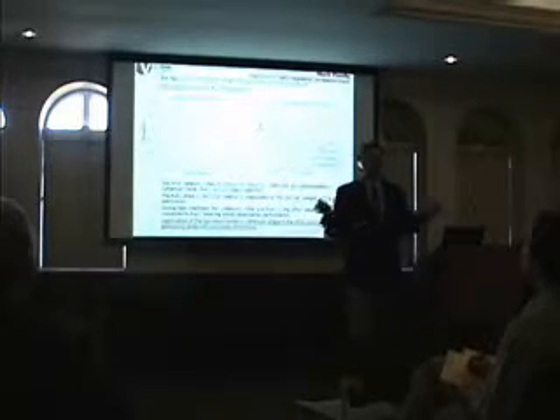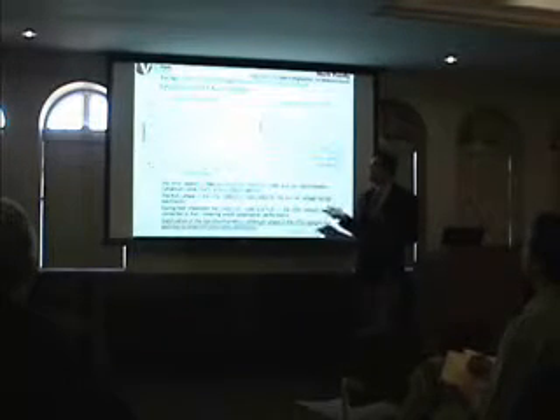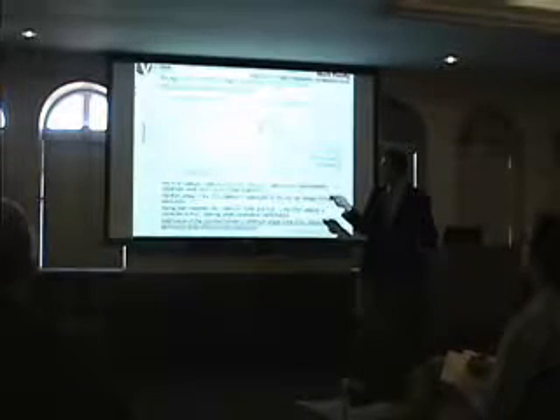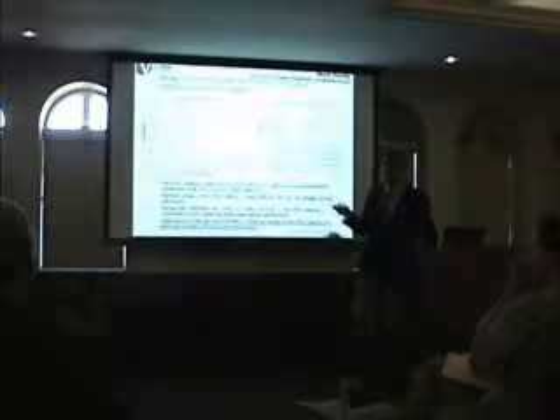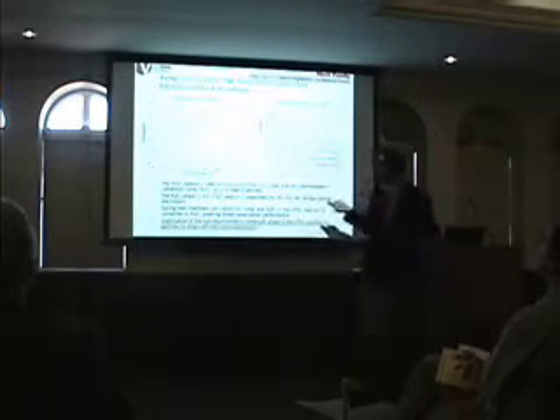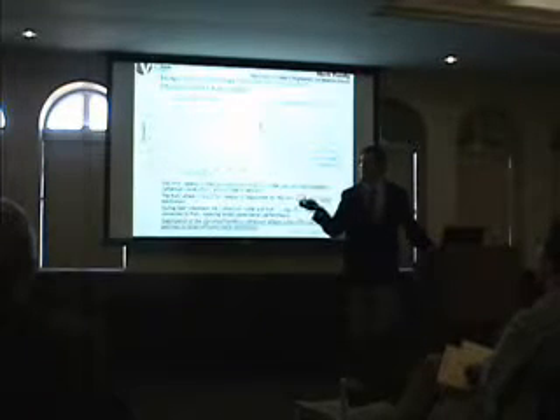We were very excited. One problem is that material only lasted about 2 hours. So 2 hours of testing, it wouldn't work anymore. And we said, oh my gosh. So we looked at different techniques of how to stabilize this material. And one of them was, let's go ahead and heat treat it. So we heat treated it at different temperatures, one at 500 degrees C, one at 700 degrees C. And we noticed one thing, that it was a lot more stable, but the performance was getting worse and worse and worse. And then we sat there and we scratched our heads. We said, oh my gosh, we made this good material, but we actually destroyed it when we heat treated it.